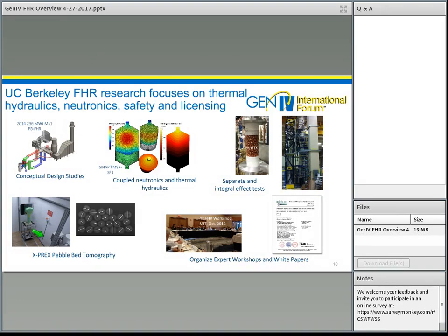Likewise, for pebble bed variations, we've been doing a variety of different pebble recirculation experiments to study pebble granular flow and develop designs for pebble bed cores. One of the interesting new capabilities is the X-ray pebble recirculation experiment facility at Berkeley, where we use instrumented pebbles that have very thin tungsten wires embedded in them. And that allows us to do 3D tomography where we track not just the centroid of the pebbles and their translation, but also rotation, which is very important in understanding how friction affects the granular flow.